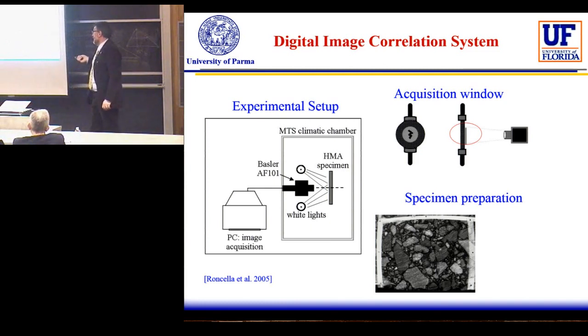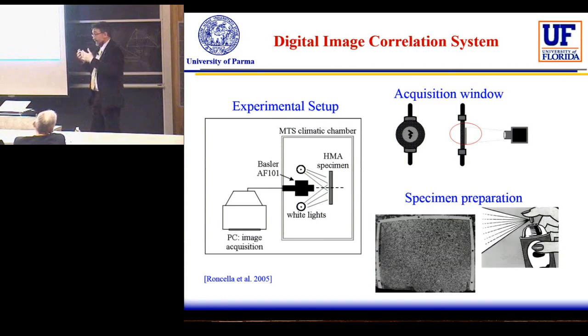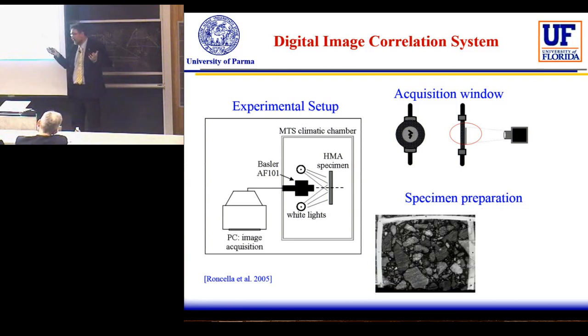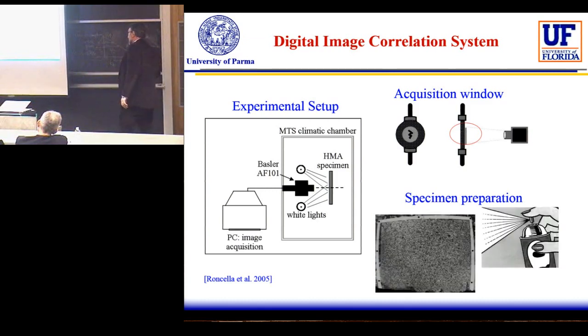And to have the right contrast, in this case a soft white water paint was used, and some random black dots in order to maximize the contrast in terms of the grayscale. If you have another material, not black like the asphalt, maybe you can do without this particular technique.